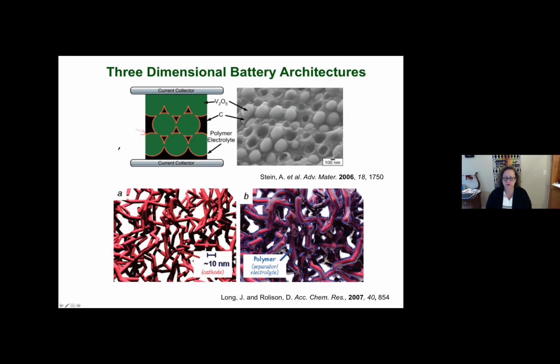This was a carbon aerogel structure that was then coated with a polymer electrolyte. And then they tried to fill in all the remaining space with vanadium oxide as the cathode material. This also had challenges with pinhole defects in the polymer. So again, sort of leaky capacitor-like behavior. But the Rolison group was able to pivot the structure and make some really beautiful capacitors and actually also move into zinc air batteries and new chemistries.